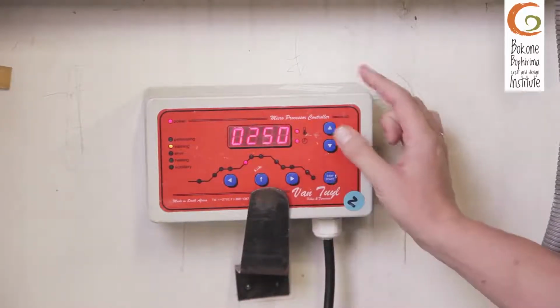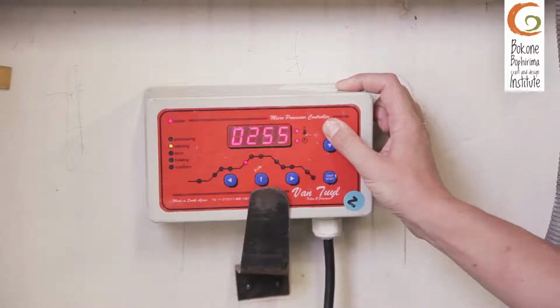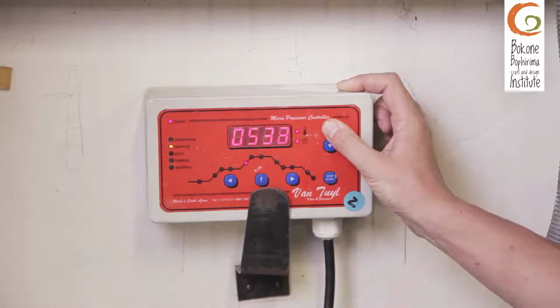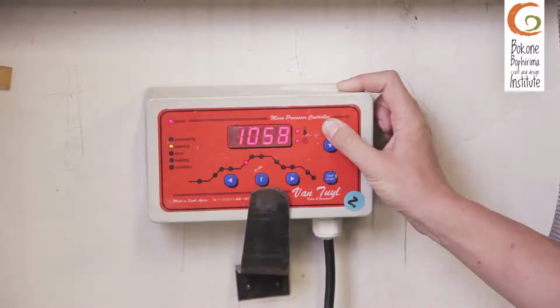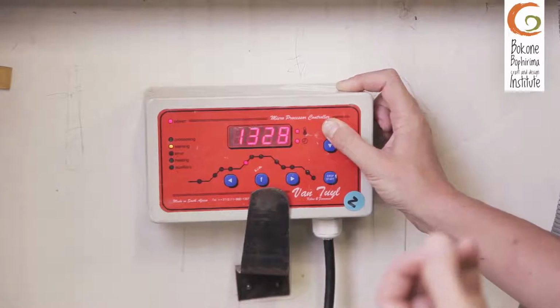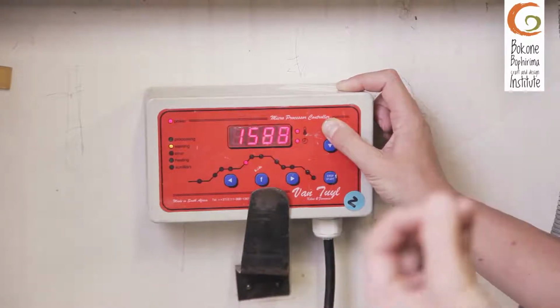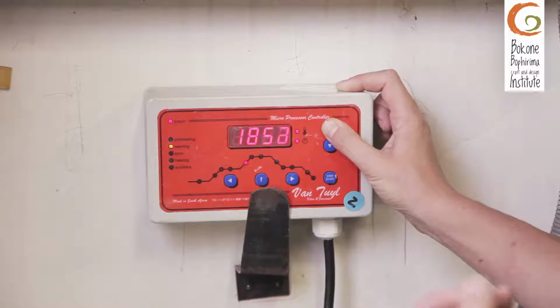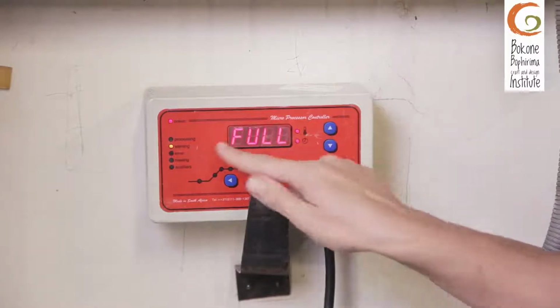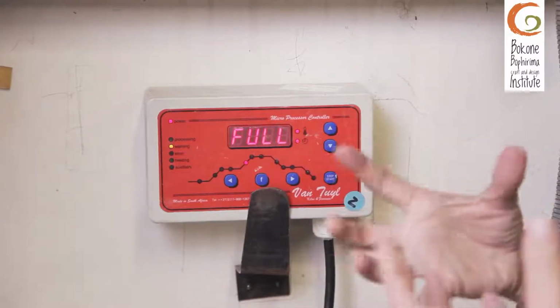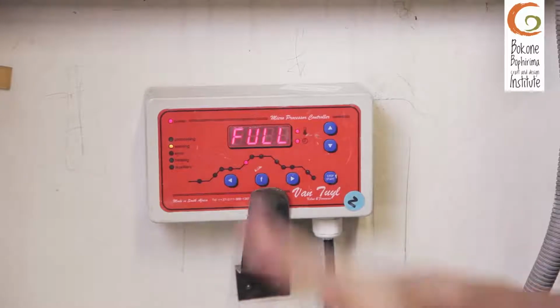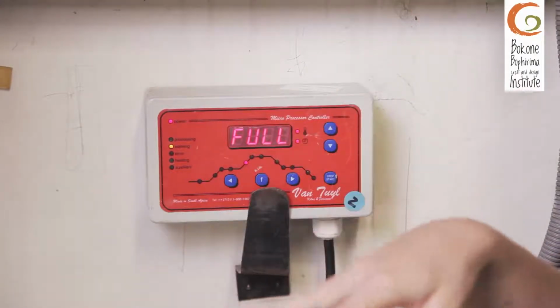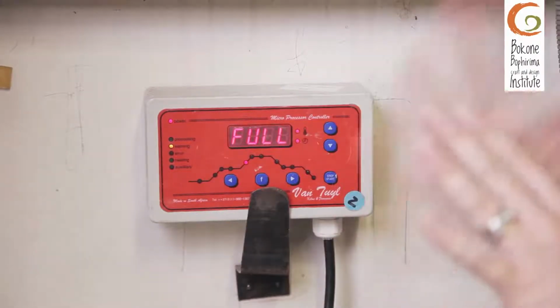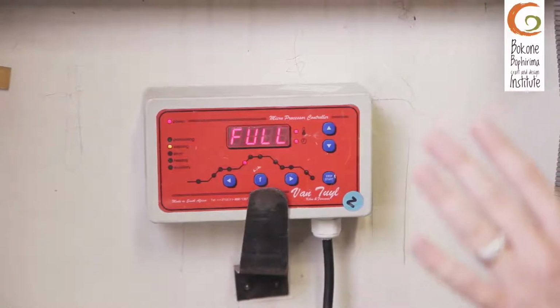Then we're going to actually go up full. Our glass has no tension in it. Because our glass has no tension in it, we don't have to worry about taking it up slowly from 580. Remember, above 580, we can work at a much faster ramp if there's no tension. So what full stands for, basically, it's basically telling me that I want my glass to ramp up as fast as possible, or sometimes it may mean as fast down as possible to cool to a certain point.